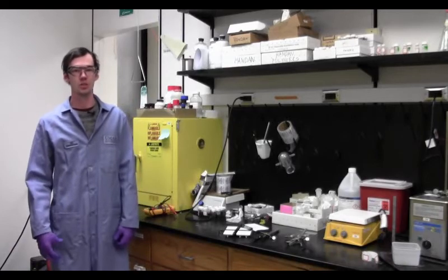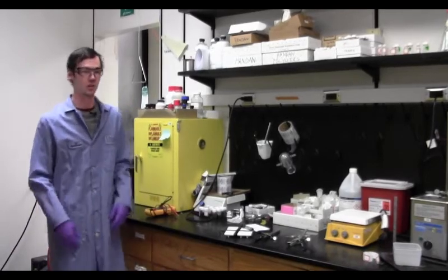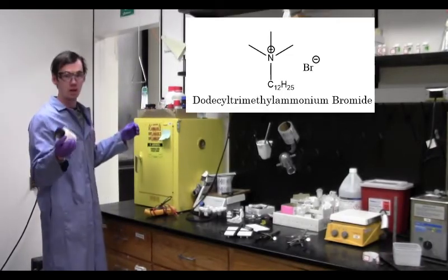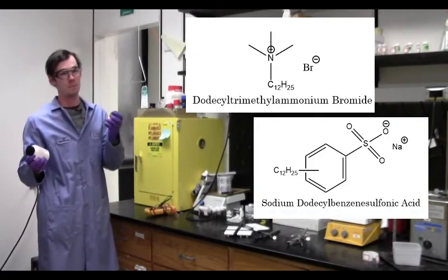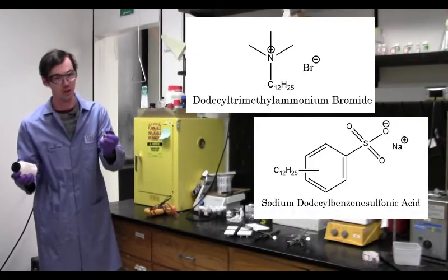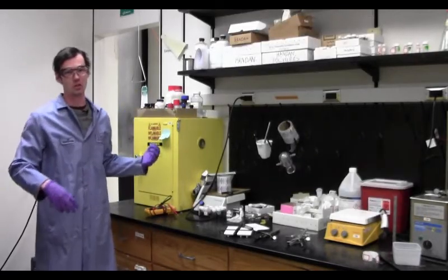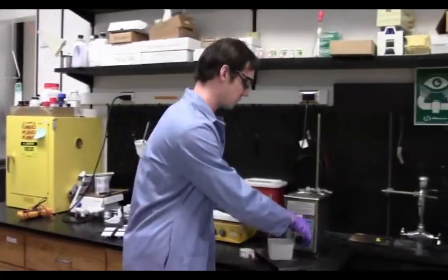I work to improve device performance and consistency by making those dye-molecules into nanoparticles. I do this using directed self-assembly and soap, or more accurately, surfactants, like this dodecyl trimethyl ammonium bromide and this sodium dodecyl benzene sulfonic acid. I mix an aqueous surfactant solution with my chloroform dye solution, and then I shake things up with sound waves.